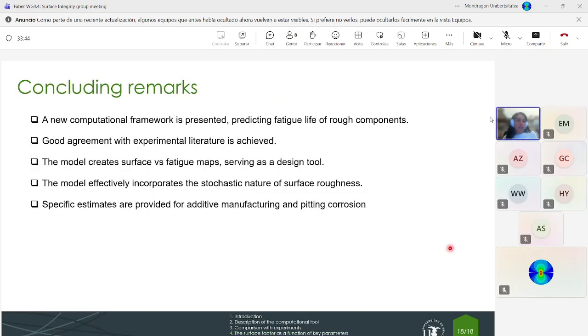So now just to conclude, we have developed a new computational framework that is able to predict the fatigue life of rough components. We have observed a good agreement with experimental data that we have found in the literature. The model is able to create surface versus fatigue maps, so we can use it as a design tool. And we have incorporated the stochastic nature of surface roughness by considering the relative margin of error, a sample size, etc.